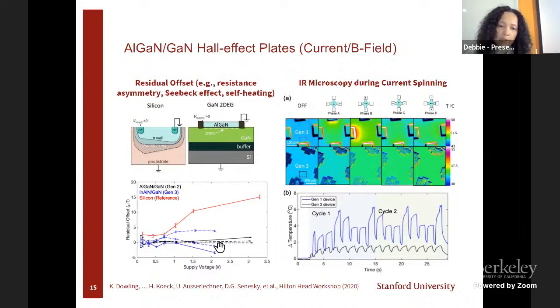So this is the offset for silicon reference. And then you can see for our two gallium nitride heterostructures, really suppression in the offset. And then we did validation studies looking at thermal profiles across the device and translating to this delta T across the device during activation and how that influences the offset.